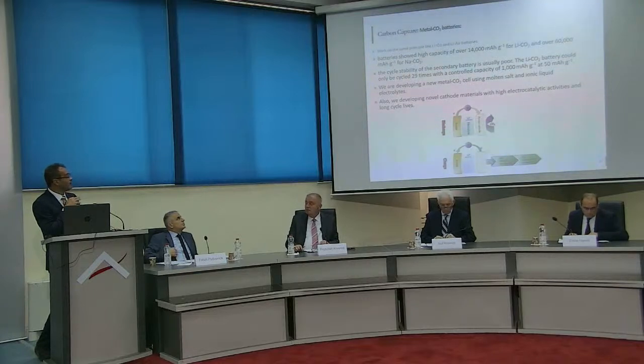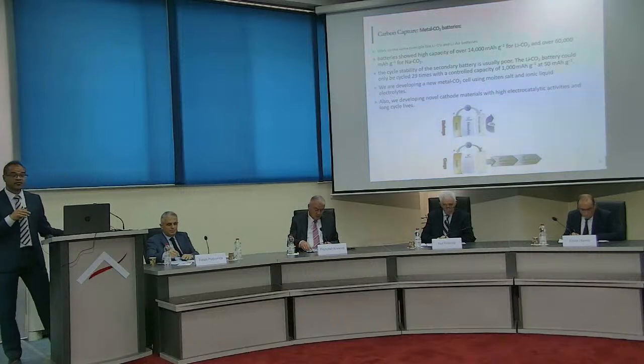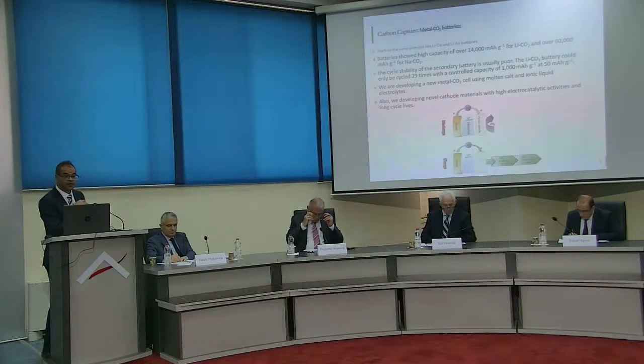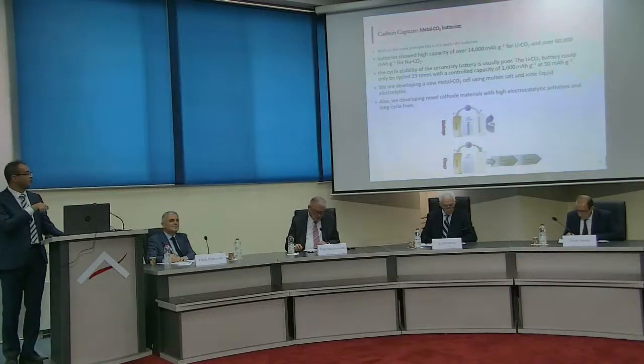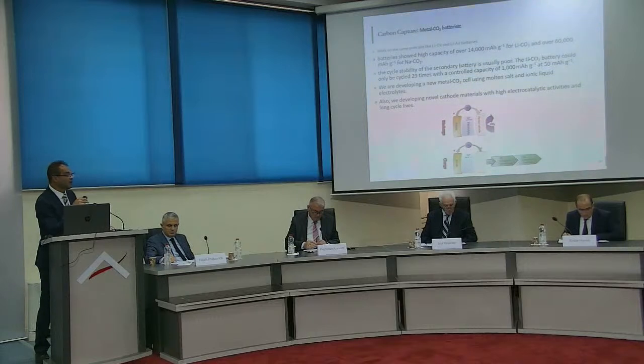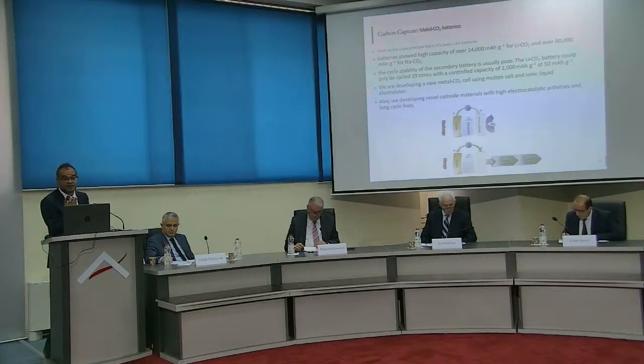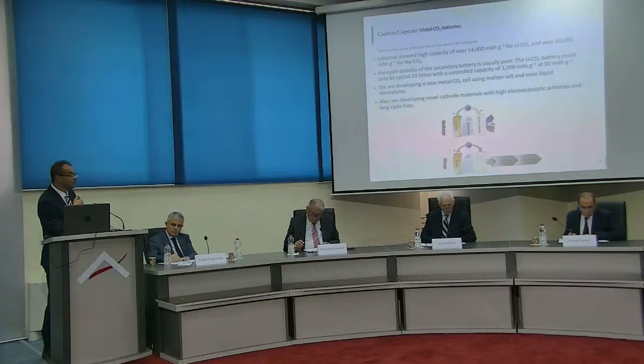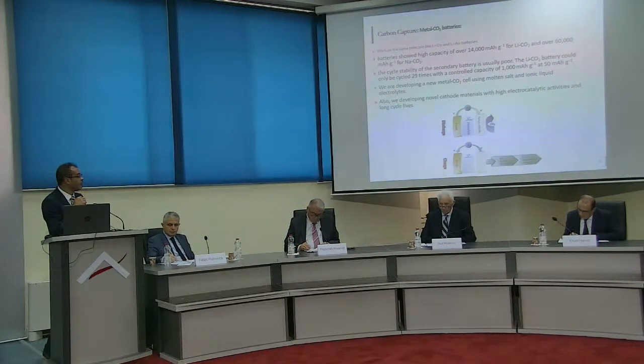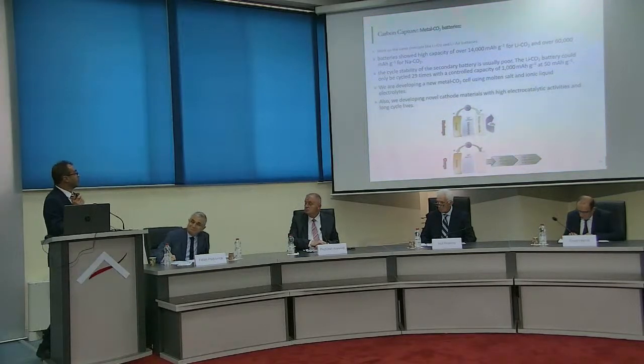This is another battery very similar to the lithium-air battery, but instead of using air or oxygen, we're using CO2. The whole idea, as you can see from this cartoon, is that during the discharge, lithium ions go to the cathode, which is made of a catalyst, and that's basically where we work. We designed this catalyst, and when you have molecular CO2, the catalyst converts it into carbonate, which reacts with the lithium ion to form lithium carbonate. During charging, it goes into the anode made of either lithium metal or lithium compounds, to decompose again into lithium and CO2. So it basically uses CO2 as the fuel for the battery itself.